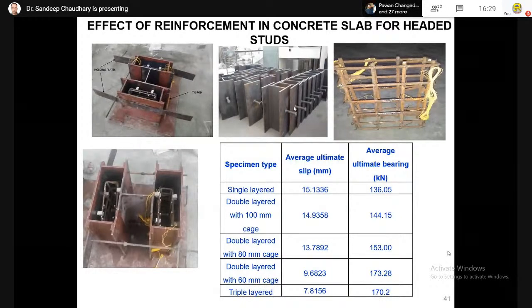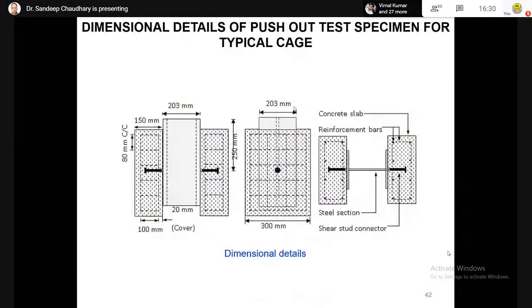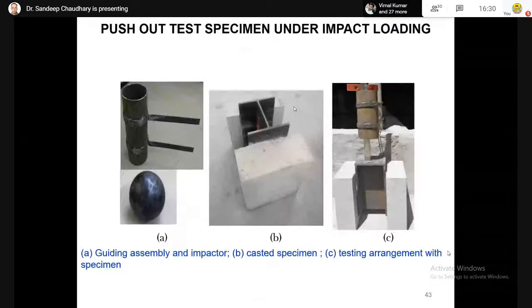In fact, when we move to triple layer, but it's not always that more number of layers are giving you more ultimate bearing. In fact, if you talk about just ultimate bearing, we observed better ultimate bearing in double layered with closely spaced spacing of 60 mm. That was 173 kilonewton. So the idea is that this reinforcement in the concrete slab also governs the load carrying capacity of these shear studs, which is mostly neglected in the code and mostly neglected by the researchers. So again, this is a niche area to work upon for future research. And these are the dimensional details of push-out test which were seen.